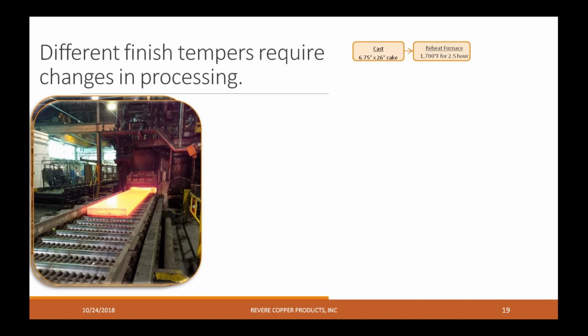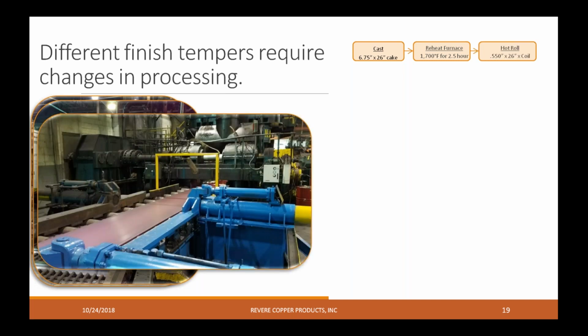So now it gets rolled, and it gets rolled from that 6 3/4 inches thick down to 0.55, which is a little bit more than 1/2 inch. But this work is all being done while the metal is hot. So this is not cold work. So when this metal comes out as a coil that's about 1/2 inch thick, it's in that reset condition. It's basically been annealed. It doesn't have directionality, it's got big grains, and it's ready for processing.